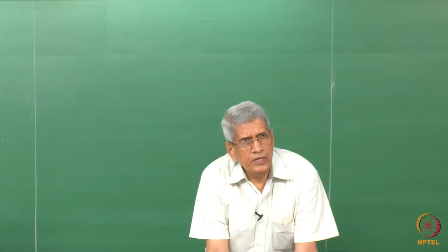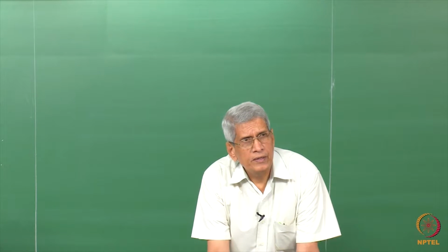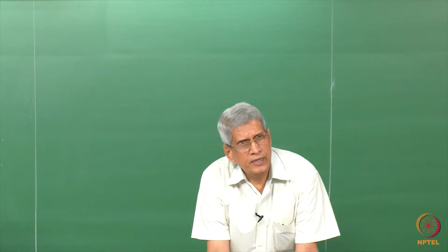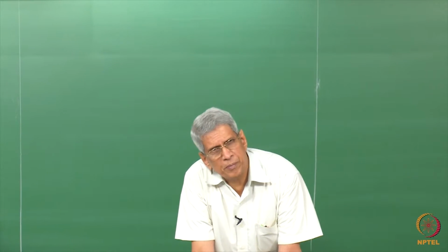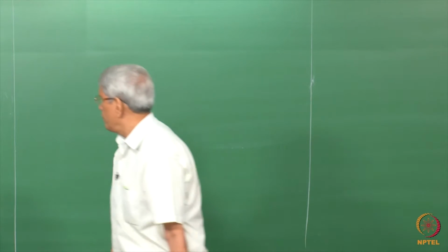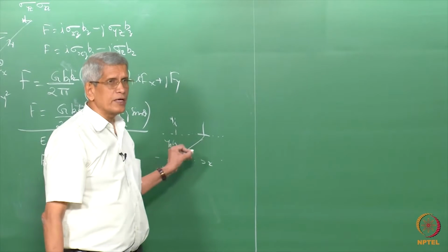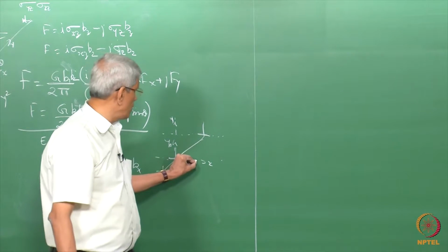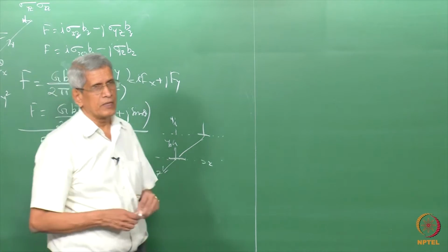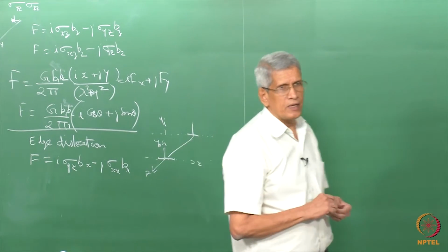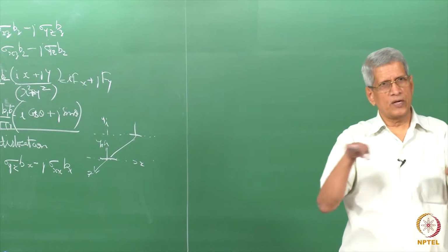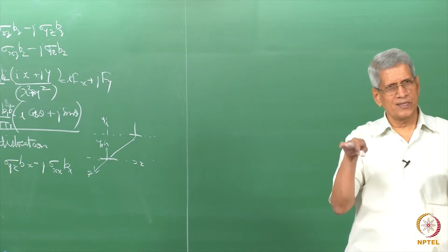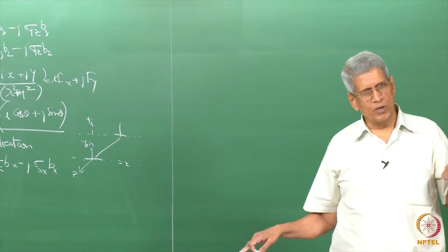Here we have to consider a few cases. Suppose this entire experiment which we are doing is assumed to be at room temperature. When we do an experiment at room temperature, the dislocations most of the time only glide on the slip line. That means that when the dislocations glide on the slip line, only the force between the dislocations in the x direction has to be considered.